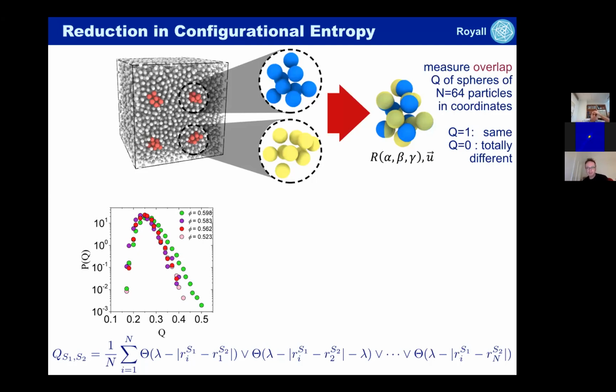I make this measurement many times throughout my material, and I can find a distribution of overlaps. Sometimes they overlap quite well, and I get a high number for Q, close to 1, or reasonably high. Sometimes they don't overlap at all, and I get a number close to 0. Shown on the bottom left of this slide is the distribution of Q. What I want to emphasize is that at the high volume fraction, shown here as 0.598, the green data, there is a tail at high Q. What that means is that there's a tail of particles with similar configurations which emerges at high Q. And this is indicative of a drop in the configurational entropy.